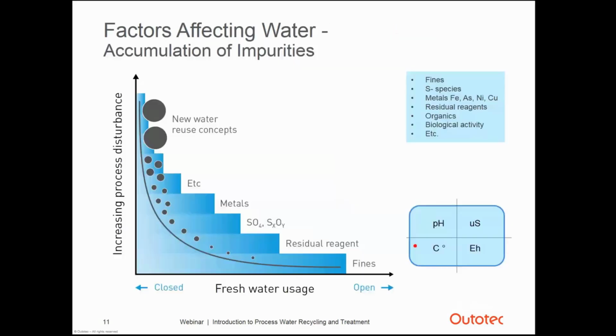Other than the tailings, accumulation of impurities in the case of recycling water is another important point. So, when we are closing the loops, for example, due to the tailings management, impurities can start to accumulate. This picture illustrates how the accumulation of impurities like residual reagents, sulfur species, metals, organics, and also biological activity increase the more we close the water loops. Process becomes unstable along the accumulated impurities, while the water parameters such as pH, temperature, conductivity, and reduction potential change. All these can have adverse effects on the flotation process.